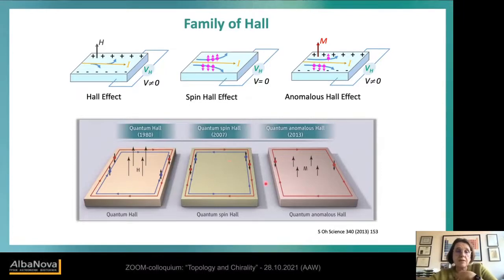The quantum spin Hall effect, the prediction from Kane and Mele, has this Hall effect without a magnetic field, because now, as we learned, the spin-orbit coupling plays the role of the magnetic field, so we don't even have to apply a magnetic field. And if we have an intrinsic magnetic field, this was a prediction of Haldane, you suppress one of the edge states, and then you have something which is the dream of a spintronic person: current at the edges, and therefore we are interested in magnetic Weyl semimetals. Exactly, we want to have this situation at room temperature, because then we can make spintronic devices.